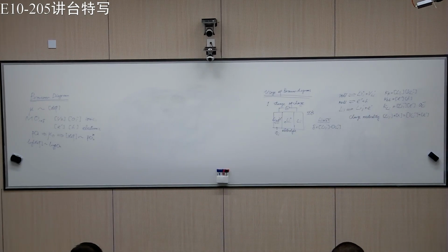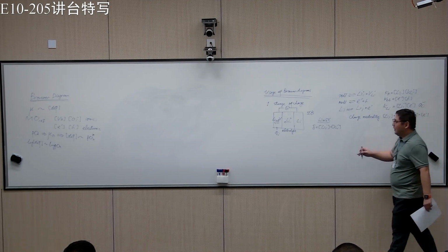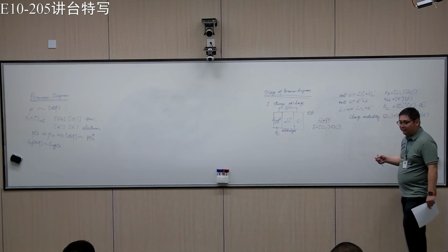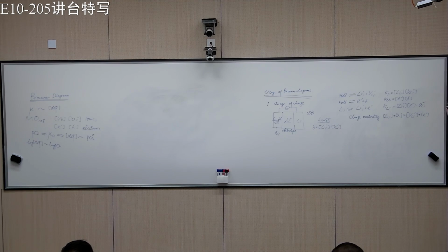Another thing we want to change a little bit here is that in the oxide system, we assume that the Kf is much larger than the Kel, which makes sense because most oxides have a very large band gap. But for a lithium-containing compound, for example lithium cobalt oxide or lithium iron phosphate, if you want to use it as a cathode material, it has to conduct some kind of electricity, right?